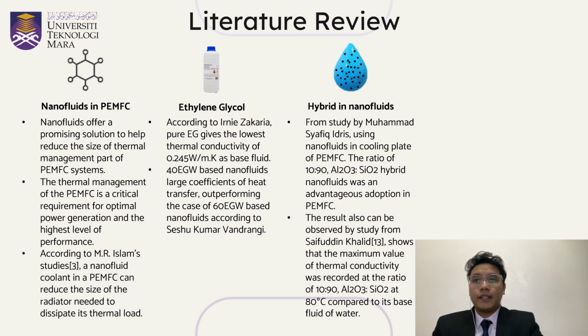According to Irnie Zakaria, the highest thermal conductivity is measured at base fluid with 0% concentration of ethylene glycol. Meanwhile, pure ethylene glycol gives the lowest thermal conductivity as a base fluid. This study summarized that the thermal conductivity decreased with increasing ethylene glycol, and thermal conductivity was also observed to increase as a function of volume concentration, as expected. Based on Seshu Kumar Vadrangi, 40% ethylene glycol and 60% water-based nanofluids, with a large heat transfer coefficient, outperform 60% ethylene glycol and 40% water-based nanofluids. Heat transfer of Al2O3 was also observed, and it also outperforms SiO2-based nanofluids at the same level of volume concentration.